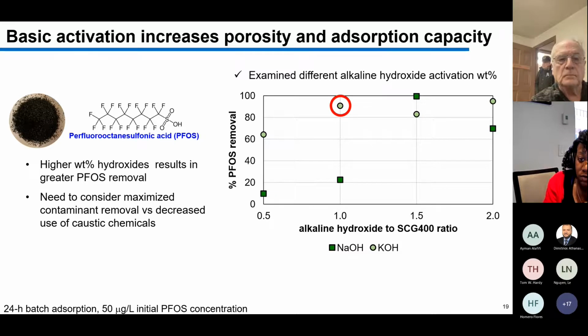So we chose 400 degrees Celsius because that was the lowest pyrolysis temperature that most carbonaceous or biochar materials are prepared using, that low temperature. And then also we wanted to keep the addition of chemical activating agents low. So we didn't want to add like 10, 15 grams of either sodium hydroxide or potassium hydroxide. We wanted to keep that low to reduce excess waste and potential toxicity with how caustic these materials are.